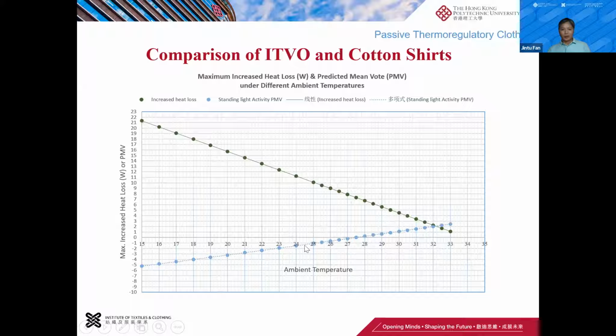So you can see, if you're wearing a cotton shirt or this kind of shirt we're testing, it is about 27.5. That is 0. That PMV of 0 means that it is optimally comfortable. Okay, and then when it comes to 29 degrees, it's 1, which means you're starting to feel a little bit warm. Okay, but if you look at 29.5 or 29 degrees, you're talking about 5 to 6 watts of increased cooling.